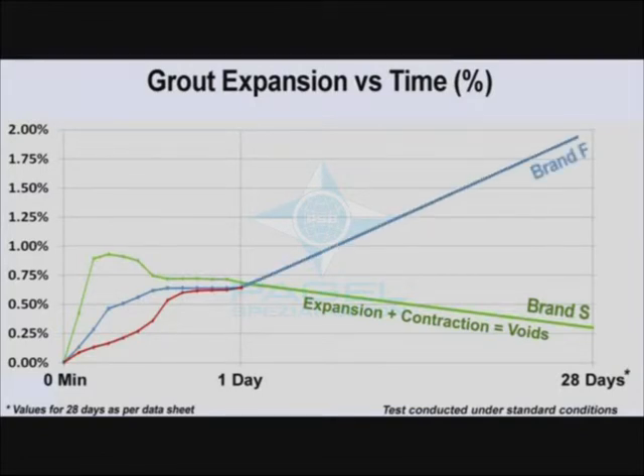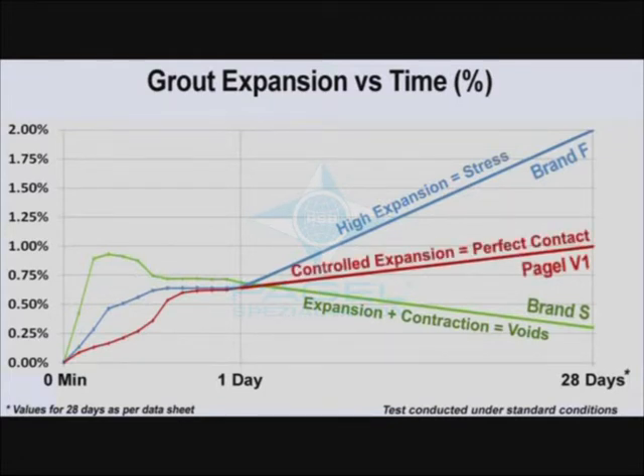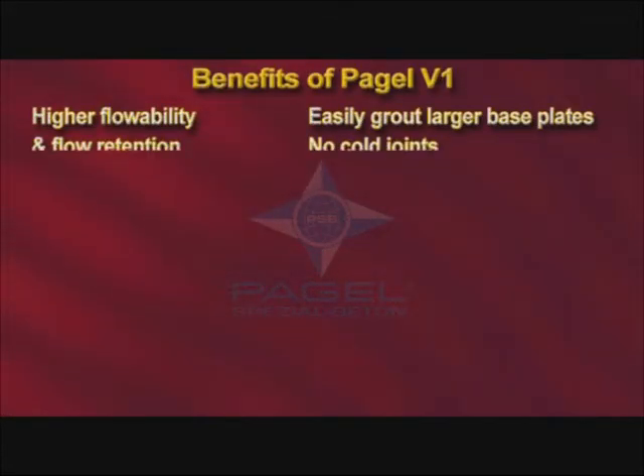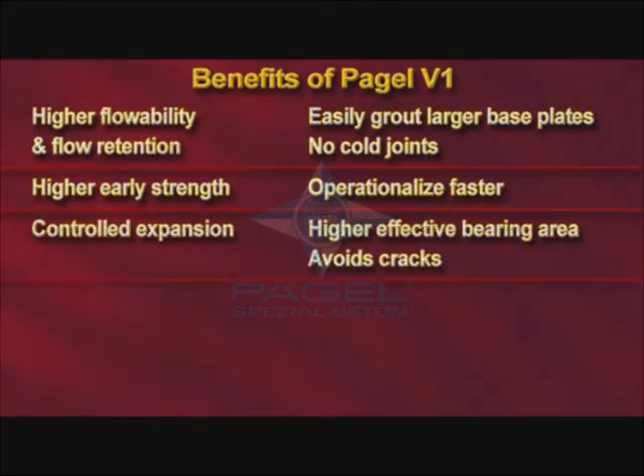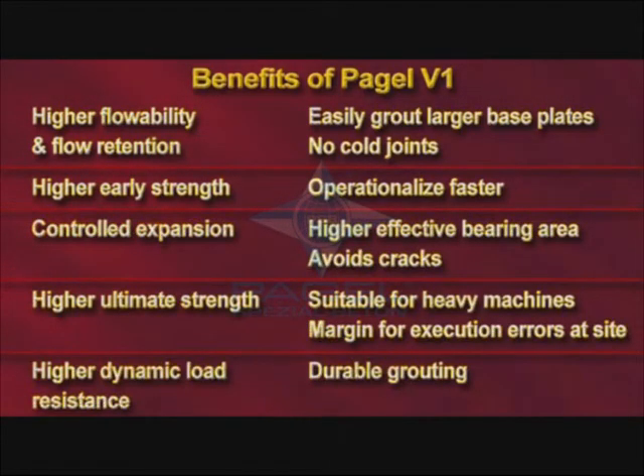Brand F expands to 2%, leading to stresses which may result in cracks. However, Pagel V1 grout reaches a controlled and continuous expansion of only 1%. This is sufficient to overcome shrinkage, yet not create unnecessary stresses in the grout during curing, giving perfect contact. To summarize, due to its several unique properties, Pagel V1 is clearly superior to conventional grouts, making it the best solution to ensure perfect contact.